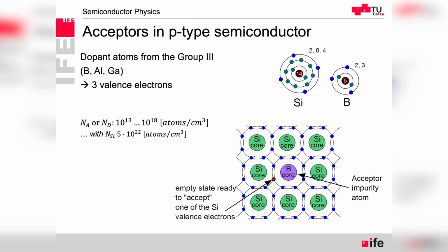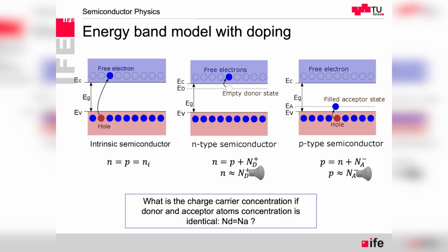The dopant atom can be smaller or larger than silicon, and that already creates some tensions in the silicon structure. So if we have very large numbers of dopant concentration, that can also change to some extent the structure of the silicon. Maybe before going to the details of this extreme charge carrier concentration, I will come back to that.